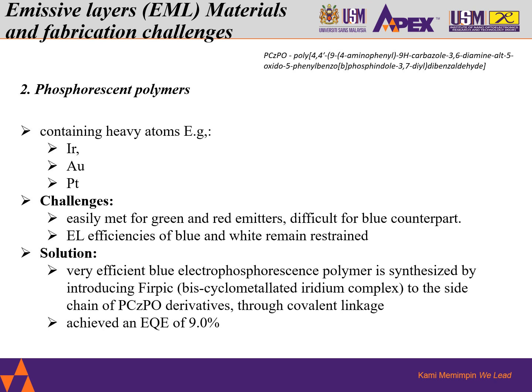Second one is phosphorescent polymers. Phosphorescent polymers containing heavy atoms such as Ir, Au, and Pt. These types of polymers can easily match for green and red emitters, but hardly realize for the blue counterpart. The EL efficiencies of blue and white PLEDs, however, remain restrained and limited. However, the solution is a very efficient blue electrophosphorescent polymer is synthesized by introducing a FIrpic bicyclometalated iridium complex to the side chain of the PCzPO derivatives through a covalent linkage. This results in blue PLED that can achieve up to an EQE of 9%.